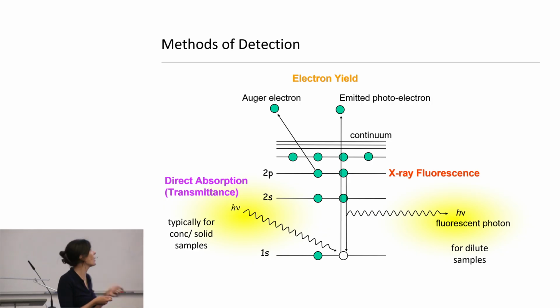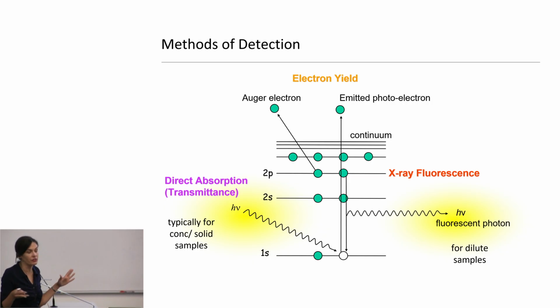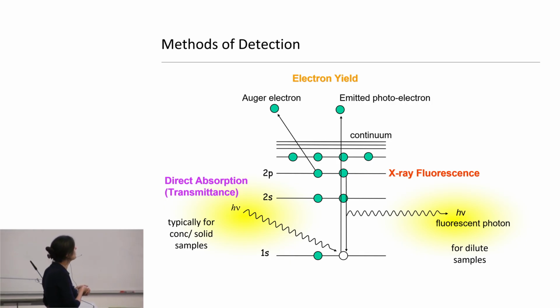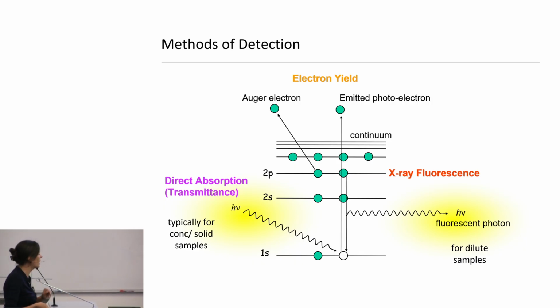And so if there's a strong probability of getting fluorescence, which is true for all of the 3d transition metals, they have relatively high probabilities of fluorescence occurring after the formation of a 1s core hole, then what we like to do is follow the emission. So this would be a 2p refilling the 1s and giving off this fluorescent photon. And so very often, we make the assumption that this fluorescence process is proportional to the absorption. And we'll talk about later how accurate that assumption is. It's an interesting discussion. But this is in general how most people are going to do hard X-ray absorption experiments. They're going to detect in total fluorescence yield. Look at all the fluorescence events that are happening.